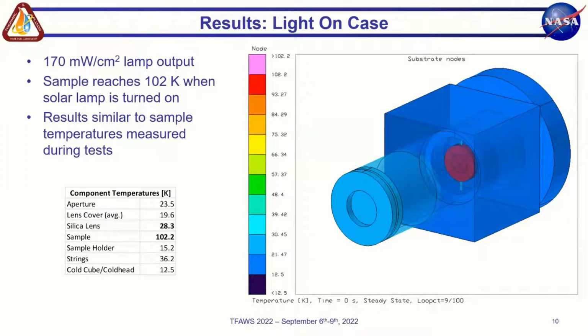And then the light on case, as the name implies, the lamp output was set to the maximum of 170 milliwatts per square centimeter. And the sample was shown to reach 102 Kelvin with the lamp turned on. So these results were very similar to the sample temperatures that were measured in the DS-Cube test. And this is mostly visible light that the sample is seeing, and it's absorbing about 1 to 2% of that light. So that's where the increase in temperature comes from. But you can see that we're still at a very low temperature of 102 Kelvin.